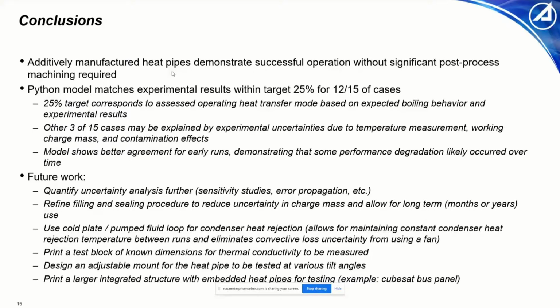Additionally, we would want to use a cold plate or a pumped fluid loop for the condenser heat rejection. We opted for a fan for simplicity, and obviously a cold plate or pumped fluid loop is going to add some complexity to design, but it would allow for maintaining a constant condenser heat rejection temperature, which would allow for better comparison between runs because your heat pipe performance is dependent on the temperature of your test. And then also it will eliminate convective loss uncertainty from using a fan.